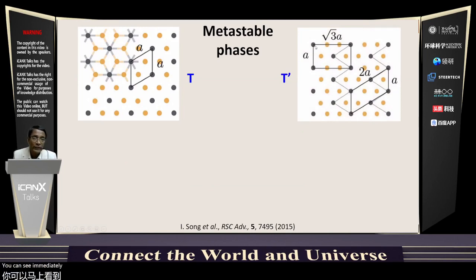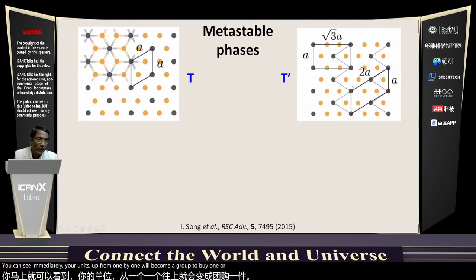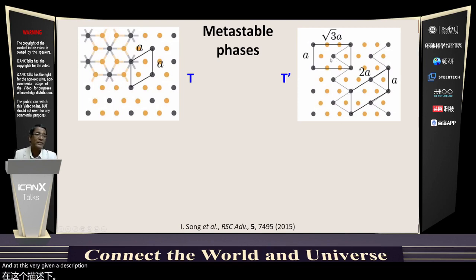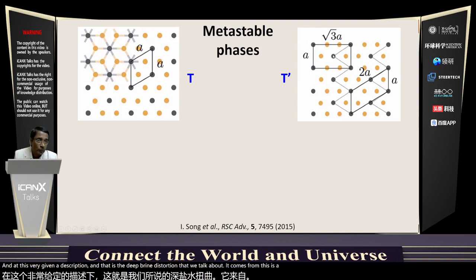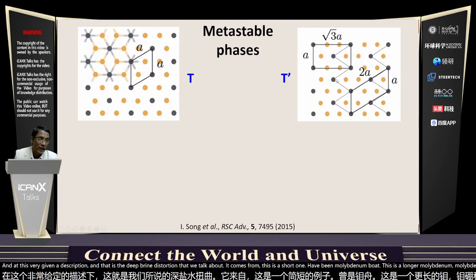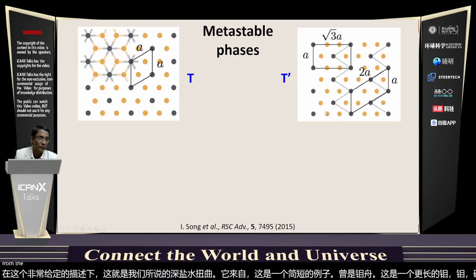And that dimerization, if I give rise to a dimerization of this kind, you can see immediately your unit cell from 1 by 1 will become a √3 by 1 or a 2 by 1 structure. And these 2 are equivalent description, and that is the T prime distortion that we talk about. It comes from, this is a short molybdenum-molybdenum bond, this is a longer molybdenum-molybdenum bond, and these dimers form a chain, and this long bond also forms a chain, alternating chains along this axis.